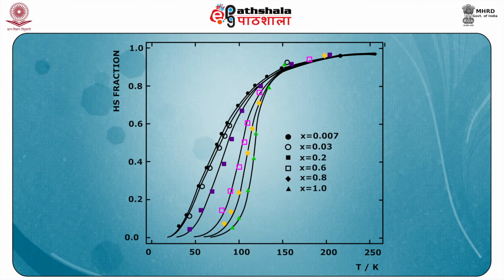Zinc was chosen in this metal dilution study because it has the same crystal structure as the analogous iron complex. The transition curve is abrupt for the neat compound where x equals 1, but becomes increasingly more gradual with increasing dilution, as is generally found for thermal spin transition in solid solutions.